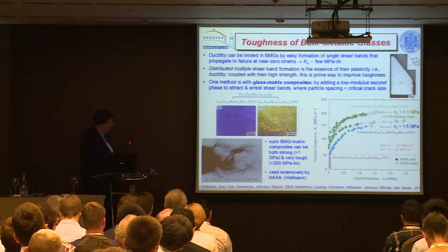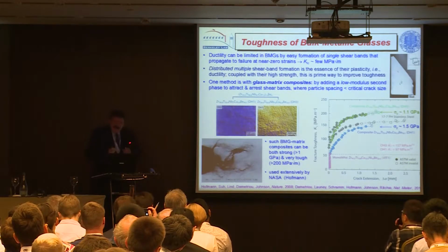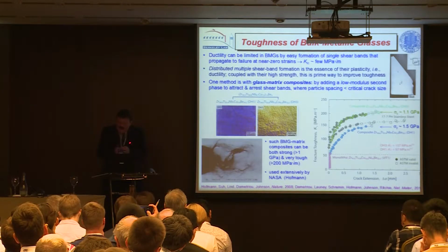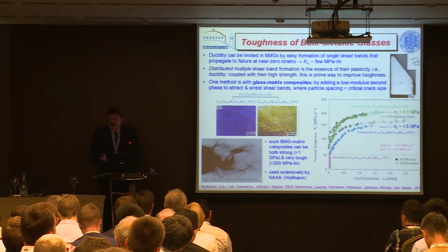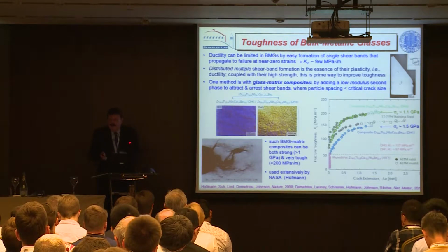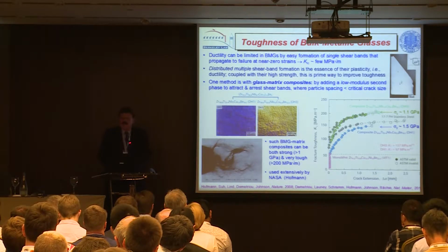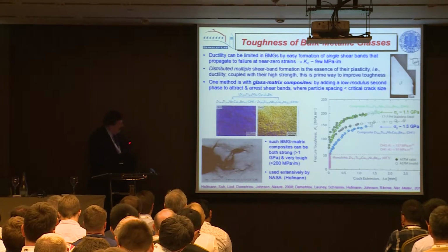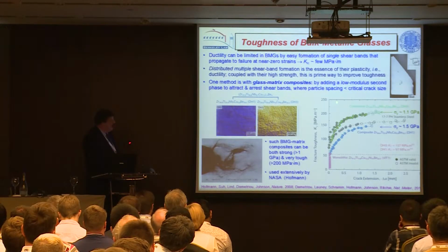It's not even crystal. It's not even amorphous. And the idea was that you match the spacing of this phase so that the spacing of the second phase in the glass is smaller than the critical crack size to cause failure in the glass itself. You're matching the mechanical and microstructural size scales. And in doing this, we did the toughness measurements for him, and we get very good properties.